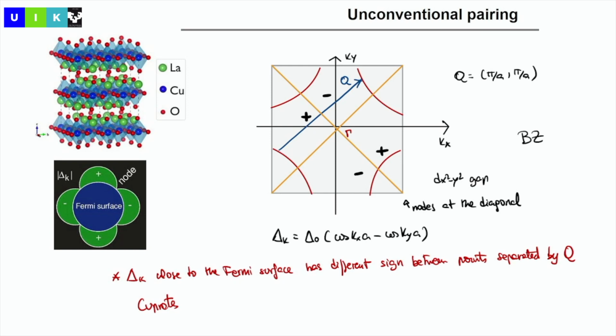The gap gives me, in fact, the symmetry of the order parameter. What we expect is to have nodes along these diagonals. This satisfies that the gap function changes sign when I do this Cooper pairing between a pair of electrons at opposite sides of the Fermi surface. This is what we call d-wave pairing, and in fact this has been observed in the cuprates. The order parameter of these materials is d-wave pairing, where the gap changes sign and you have these nodes along the diagonals of the Brillouin zone.